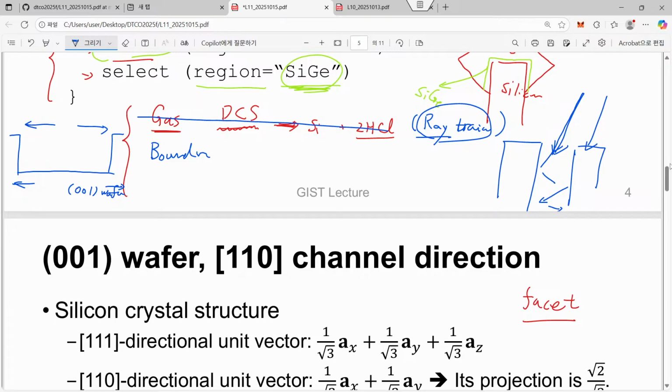Then we are now trying to grow something. Then obviously there will be something strange due to this boundary condition. But at the main body of this opening, we will have just growth of the 001 surface that is uniformly grown, and only the part related with this retarded interface will be delayed, so we will have this behavior.